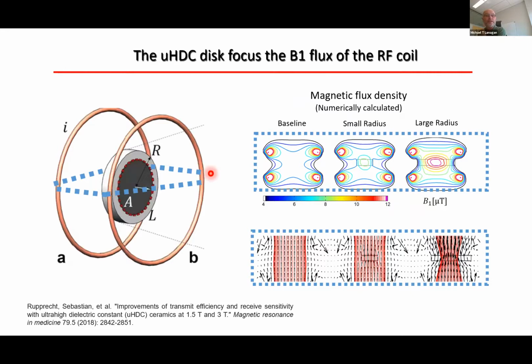So there are some simulations showing the effect of the ceramic disc, the high permittivity disc shown here. And as we can see, here's the baseline data without the ceramic discs. And as we start adding the ceramic disc, we can see an intensification of the magnetic field from that displacement current. So it's just some fundamental ideas around why we use dielectric materials to enhance magnetic fields.